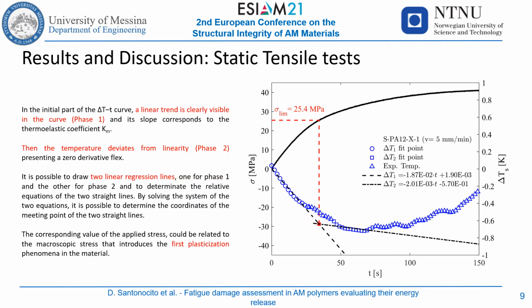During static tensile tests, the evolution of the specimen's surface temperature has been evaluated by means of an infrared camera. The applied stress is reported versus the specimen's surface temperature variation, estimated as the difference between the instantaneous temperature and the initial temperature of the surface recorded at time 0. The temperature data has been filtered with the Loess filter with a data span of 5% in order to reduce the outliers and highlight the thermoelastic trend.